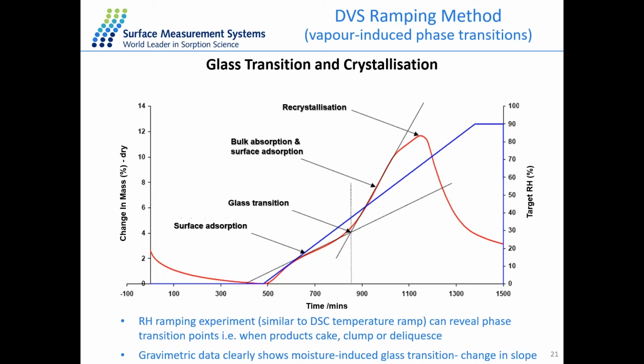And here's the result for the lactose sample again. The red line is the change of mass for the sample. So the sample is losing mass at first because of the drying stage, just the flow of the carrier gas. And at the very beginning, the increase with humidity is quite slow. It's due to the surface sorption of the material. And then after a certain point of humidity, the increase of the mass becomes dramatic. That's because the water molecules are not only on the surface this time, but also penetrate the surface and go to the bulk of the material. So the change in the middle here accounts for the glass transition of the material.